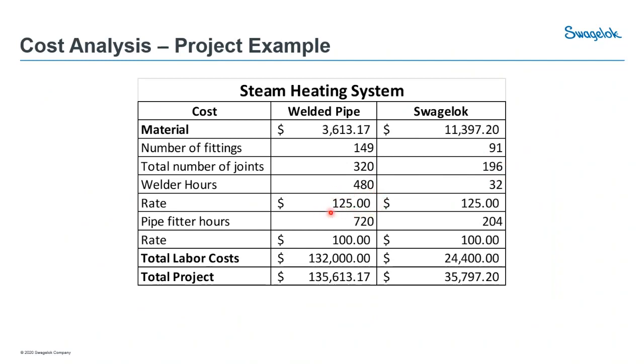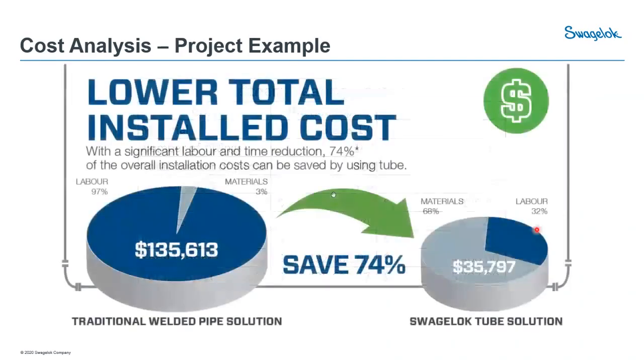Now, this was an example rate that was used in the example by the contractor. But when you compare 480 hours versus 32, you can see that it really adds up quickly. Then when we go to the pipe fitter hours, over 700 compared to 200 on the tubing system. So if we look at that side by side, really it's that lower total installed cost. So that piping system was about $135,000, including the material and the labor. Now the labor was actually 97% of that cost. The material was only 3% of the total project cost. So if we went to an example here where we save 74%, that's where the labor was actually 32% of the cost. So the materials is 2/3 of your value in the $35,000.